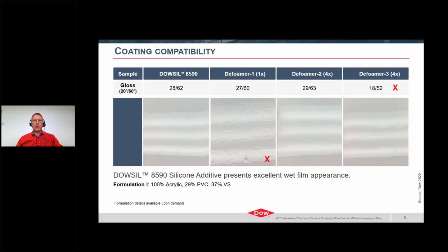Those 4 defoamers were compared in an acrylic-based formulation, characterized by a 29% pigment volume concentration and 37% volume solid. And in this case, we show the results or the observation of the film based on drawdown on test charts. We can see that the formulation containing our featured product shows excellent appearance relative to competitor 1, which presents many coating defects. Defoamer 2, again, the silicone with good compatibility, shows a good appearance and good gloss level, similar to our featured product, but required 4 times the loading to achieve the same performance level.